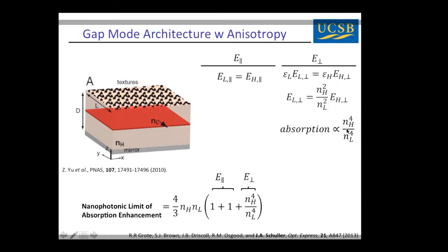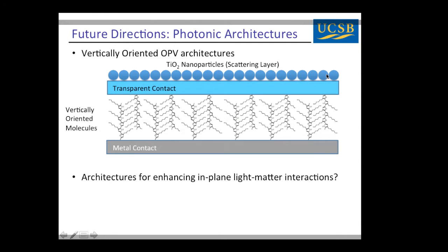Okay? So the idea here, to conclude, is that we made measurements of optical anisotropies to learn something about materials, but what that informed us was that, this is something that had largely been ignored, in photonic architectures for light trapping in solar cells or LEDs, it's very important to take into account these anisotropies, okay? Because the field enhancements are quite different for the different types of fields. Okay? So from a purely optical perspective, we think the ideal OPV architecture might be something like this. You have a scattering layer, which takes your incident sunlight, distributes it to all the angles, and you design your organics so that most of the absorption corresponds to out-of-plane oriented dipoles. Okay? Similarly, we're also looking at different types of architectures which are specifically designed to enhance your in-plane light-matter interaction.